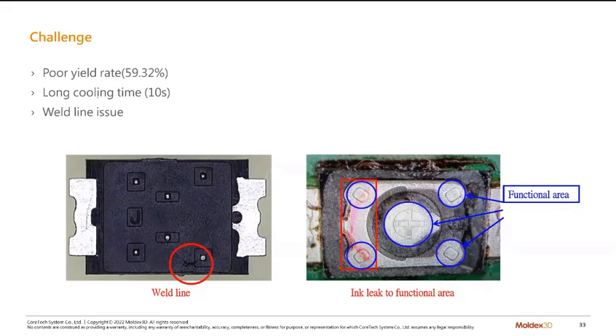Okay, so in this case, the real problem is not really the weld line. The problem is the weld line leads to some kind of crack or gap on one side of the part, and they have to hire an operator to do a checking process. They just drop some red ink on this side and wait for a while. If the ink flows to the other side, then this one failed, because this kind of behavior will make this functional area nonfunctional.